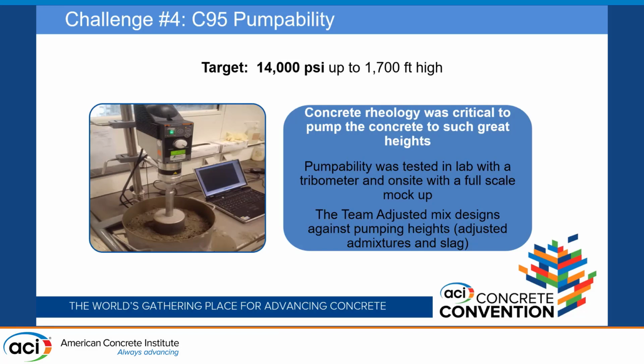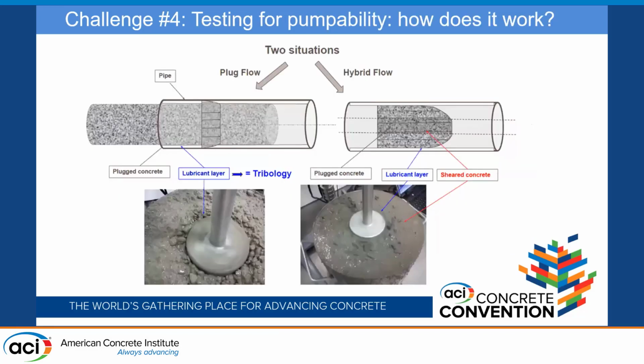This project gave the Lafarge team the opportunity to validate the simulation tool and pump pressures measured on site. We used it mainly on this project to benchmark different admixtures and adjust dosages versus growing pumping heights. We also used the tribometer and simulation tool in order to benchmark different sources of slag. As I said, the slag earlier was critical to the workability of the mix.